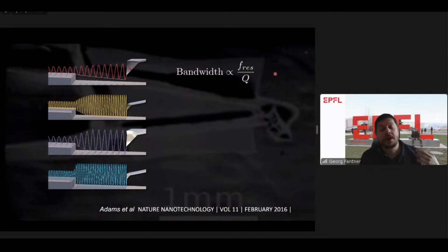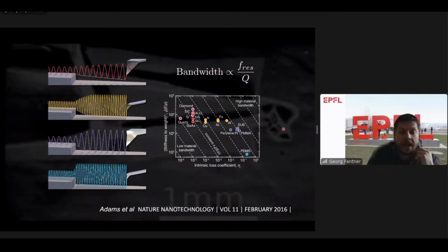Everybody was optimizing the shape, but the material was pretty much always very standard microfabrication materials, silicon or silicon nitride, as we know them from the semiconductor industry. But if we actually look at what material parameters determine how fast such a cantilever reacts, so what determines the resonance frequency and the Q factor, we can plot on the y-axis the mechanical properties that determine the resonance frequency, which is Young's modulus and the density.